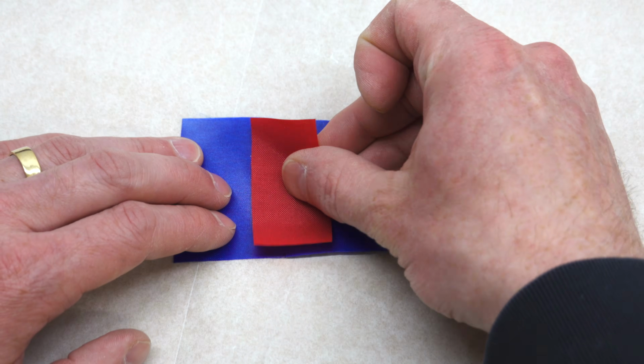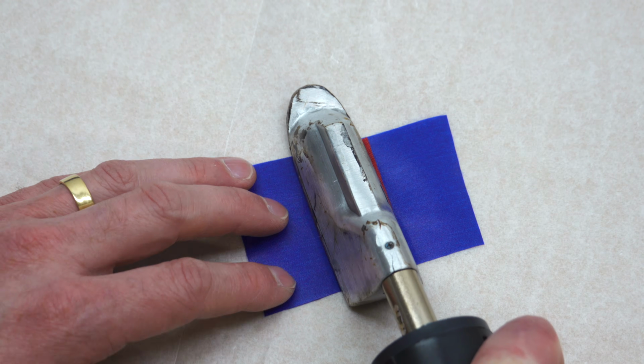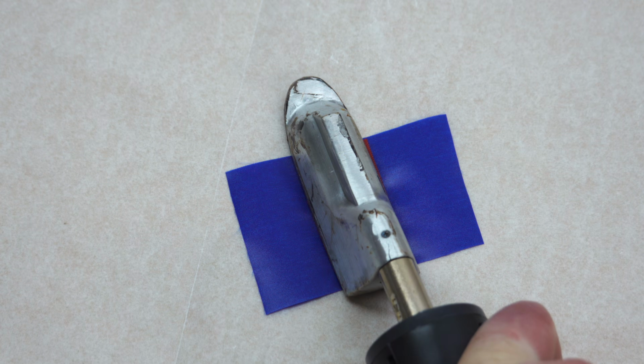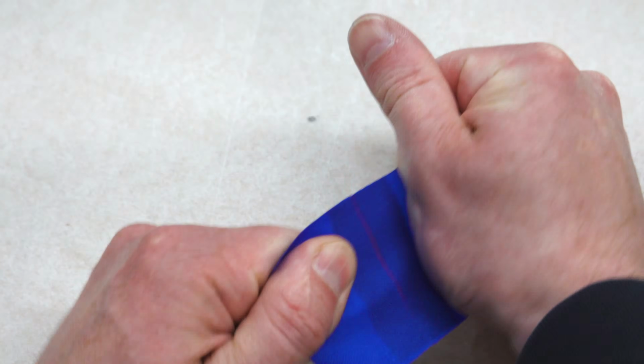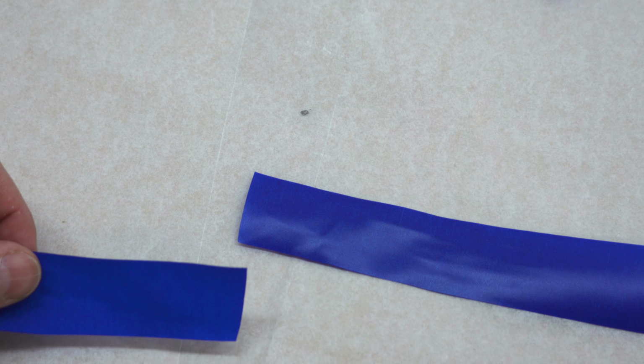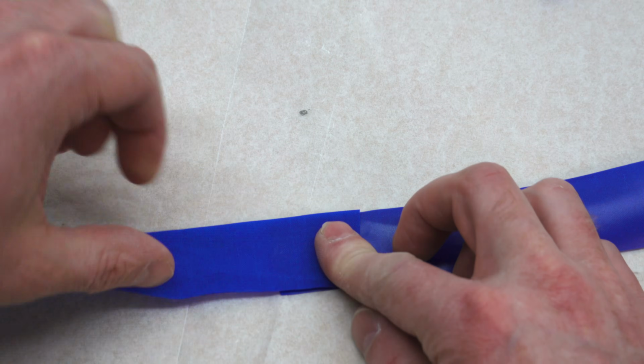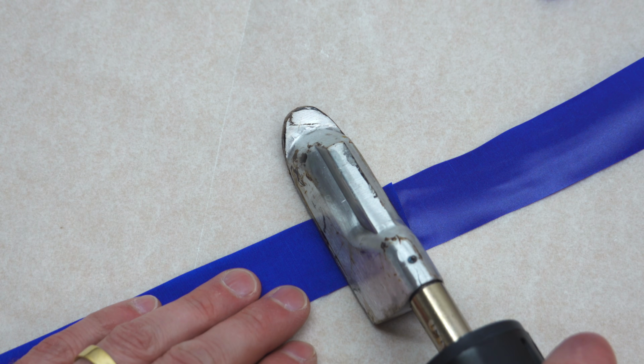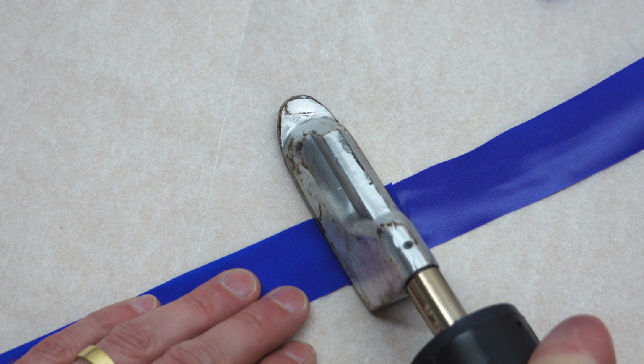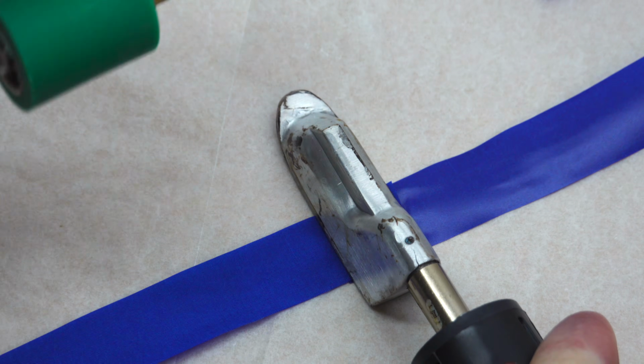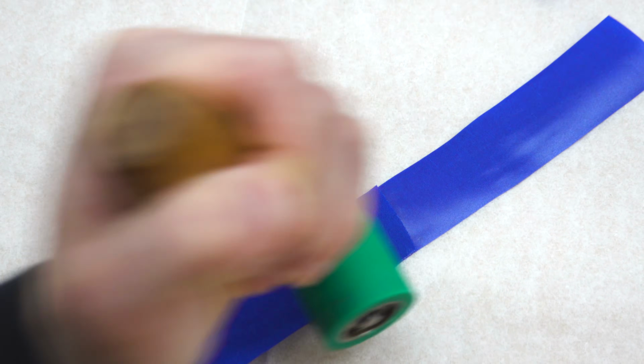Other seams are simply overlapped like this, so there's no peeling force applied, only a shear force. In one of my old videos, I demonstrated how I could hang my whole body weight from a 1-inch strip of fabric with an overlap weld like this, and when it broke, it was the woven fabric that ripped, not the weld. That's why I can confidently say that additional sewing or gluing wouldn't make these seams any stronger.